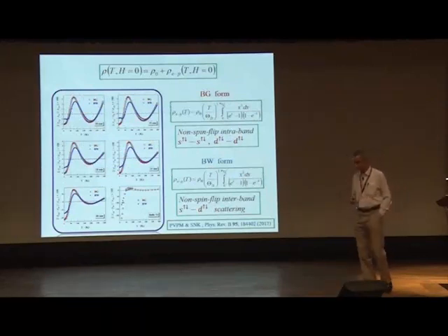Now we go step by step and see how we can identify first which are the dominant scattering mechanisms, and then try to quantify them in terms of their magnitude. What I am showing you on this axis is the percentage deviation, that is deviation of the experimental value from the theoretical fit. Okay, that's what I am showing here. This is rho experimental minus rho fit divided by rho experimental, times 100, in percentage.